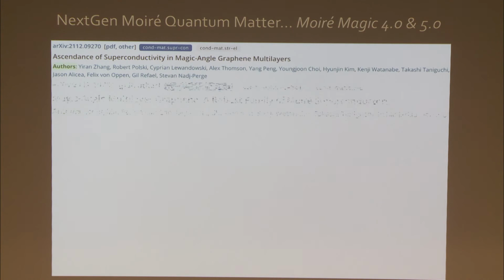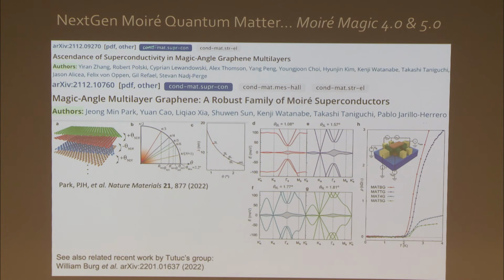Now, not only we have found that 3-layer superconducts, but earlier this year, 3 groups again reported the discovery of superconductivity in magic angle tetralayer and pentalayer graphene. Also, again, with different magic angles. You can see the electronic structures here. They all have flat bands, and at different twist angles you can get superconducting traces. So now we have actually a family of robust Moiré superconductors. Okay, this is something which is very generic, and that will continue to grow, as we keep making more and more devices.